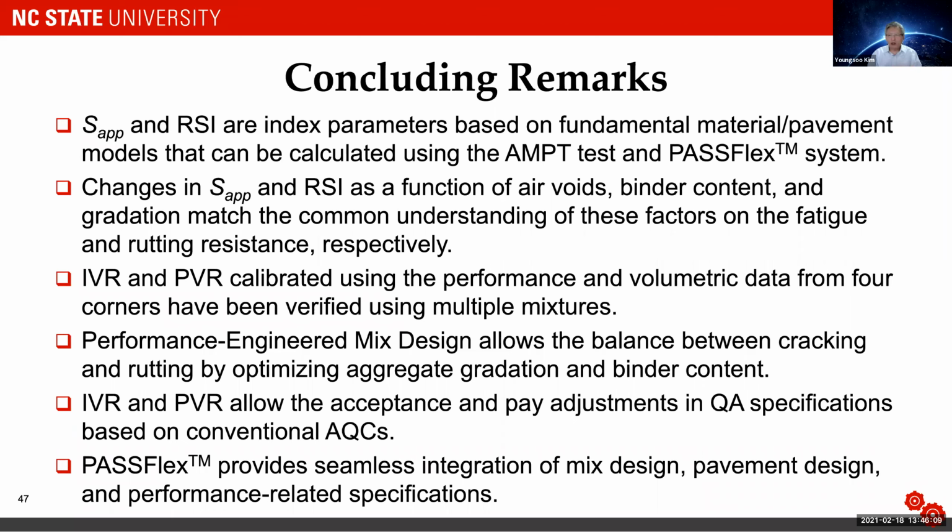And we have demonstrated in multiple mixes that changes in Sapp and RSI as a function of air voids, binder content, and gradation match the common understanding of their effects. Okay. And IVR and PVR calibrated using 4-corner data have been verified using multiple mixtures so far. And PEMD allows the balance between cracking and rutting by optimizing aggregate gradation and binder content.